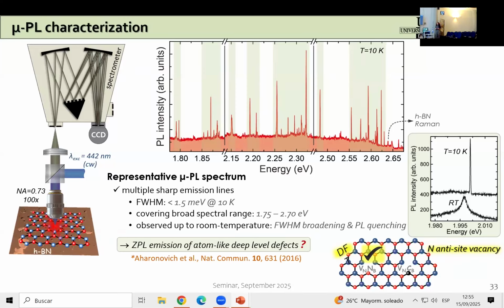Now, many experiments in different groups on hexagonal boron nitride monolayer, multi-layer flakes, as well as crystals, have seen such sharp lines, and they are attributed to the zero phonon line emission coming from atomic defects that can confine energy levels deep within the band gap, and they can act, as I've commented before, as recombination centers for the emission of single photons. Now, I also mentioned that it is still not very clear what the actual chemical structure is of the defects that are causing such sharp emission lines.